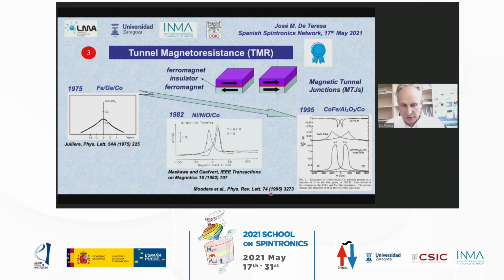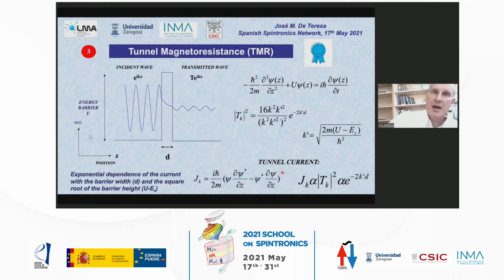A few years later, the group of Jagadeesh Moodera at MIT grew, in a very reproducible way, these cobalt iron, alumina, cobalt trilayers, and then he was able to observe magnetoresistance greater than 10%, which was reproducible. And then the research on this topic started to explode. So what is the idea behind this effect? You know that quantum mechanics allows a tunneling effect, a phenomenon whose probability depends exponentially on the width of this insulating barrier. So if one tries to solve the Schrödinger equation of an incident wave, you will see that there is a certain transmission probability.